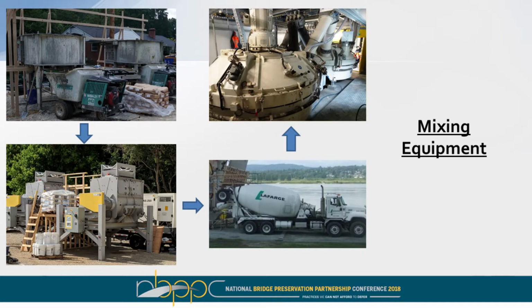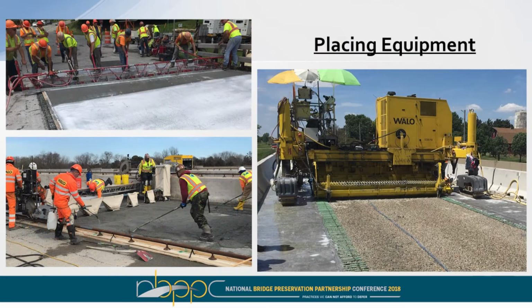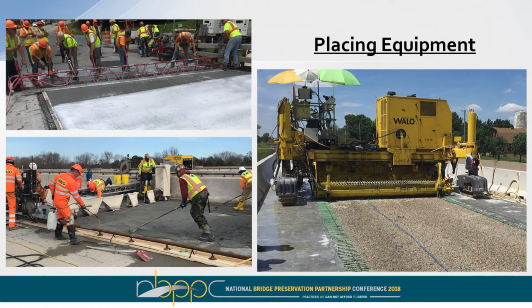But as your project size grows, you might have need for a ready-mix truck or even an on-site batching plant of sorts. And then placing equipment, we use fairly regular equipment. The top left there is just a vibratory screed, steel screed, that was used on a couple of these projects. The bottom left is basically the same thing, a vibratory screed, but a little more refined. The contractor on this job had it on a rail-mounted system to kind of give them more ease of movement with the system. And on the right there is a large placement machine that's kind of been specially designed for placing UHPC, kind of originated in Europe. It's more used for larger placements where it would justify something of that size.